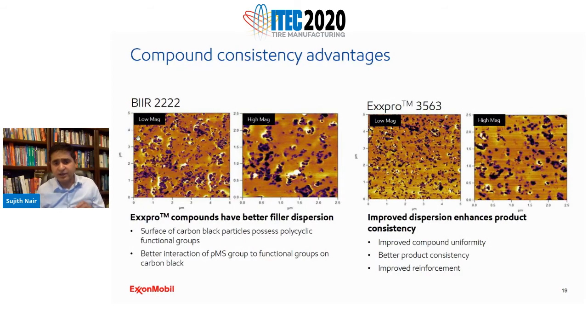This is a bimodal AFM image of bromobutyl compared with Exxpro. I've shown a low magnification and a high magnification. You can see that Exxpro compounds have a much better dispersion. On the right side, you have Exxpro. On the left side, you have bromobutyl. Both in the high mag and low mag, you can see that the carbon black particles are much better dispersed in Exxpro than bromobutyl. So we think that this gives multiple different properties.